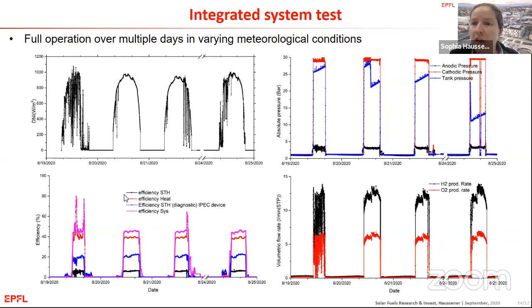Last thing are efficiencies. It's always a bit difficult to assess it, but if we look at the system level, solar to hydrogen efficiency, we have about 5% solar to hydrogen efficiency based on the standard Gibbs-free energy. If we look just at the device level, we have in fact 20% solar to hydrogen efficiency. So we lose a lot in the optics because the concentrator we have is not, let's say, a very high performant one. And then if we also consider the excess heat which we produce at temperatures in the range of 70 degrees, then we have truly a cogeneration system, and we can put system efficiency producing hydrogen and heat to almost 45%.